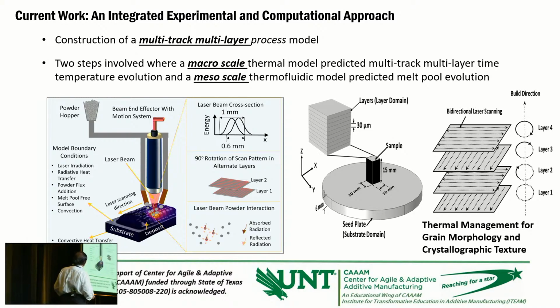This is the same thing shown here. This is how the scanning is done in each layer, rotation through 90 degrees. The computational approach developed for this kind of process involves two steps. One is a macroscale thermal model, which involves the prediction of multi-track, multi-layer effects, and the mesoscale, which is more confined to the thermofluidic model predicted in the melt pool, because the material melts and then solidifies. So what happens within that melt pool is predicted by the mesoscale model, and that is repeated from layer to layer.